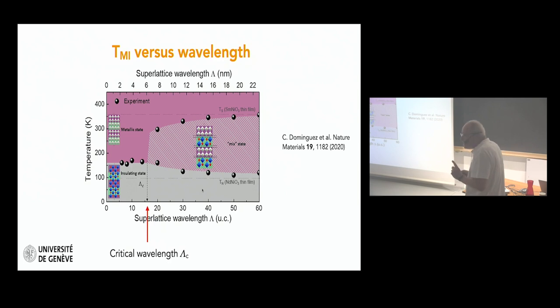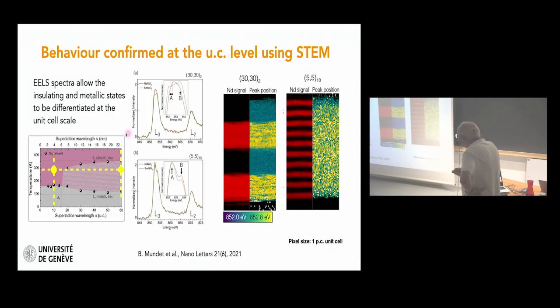But before I show you this, let me tell you that we used a beautiful STEM analysis to make sure that what we were seeing in this diagram here was correct. So what we did, we selected two samples for scanning transmission electron microscopy analysis at room temperature. One is a 5 unit cell sample, where both materials should be metallic, and one is a 30 unit cell sample, where samarium nickelate should be insulating and neodymium nickelate should be metallic.